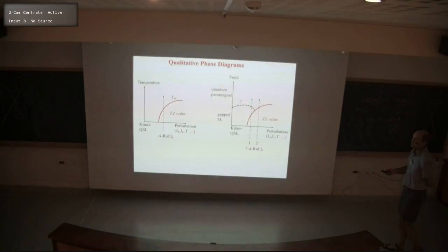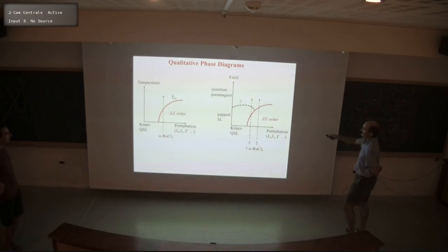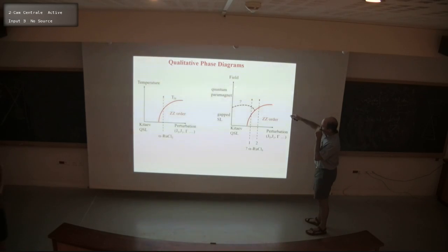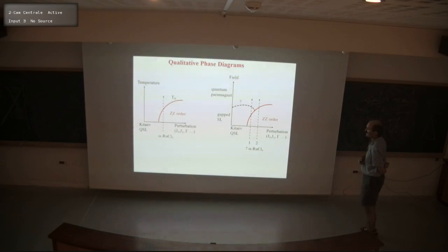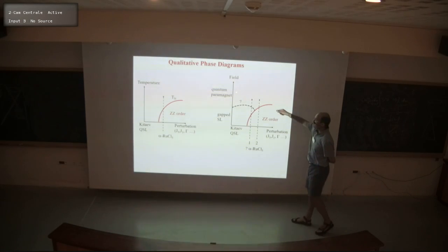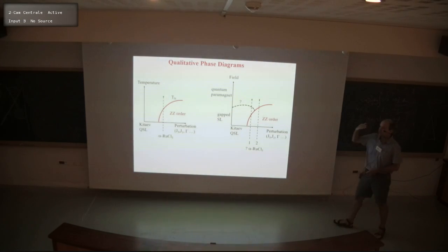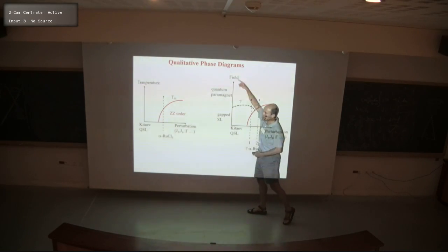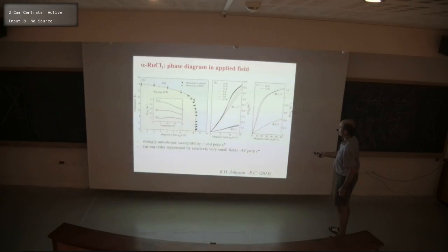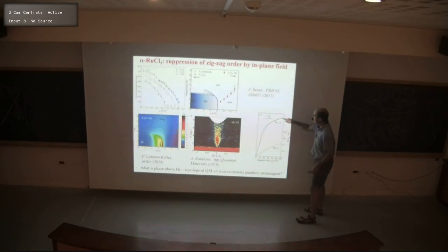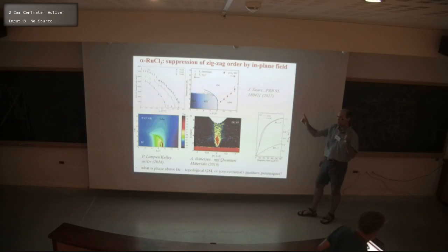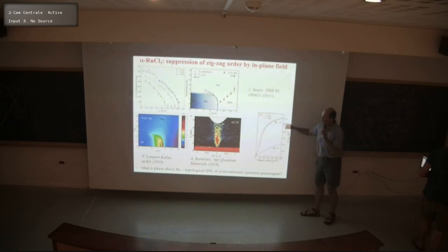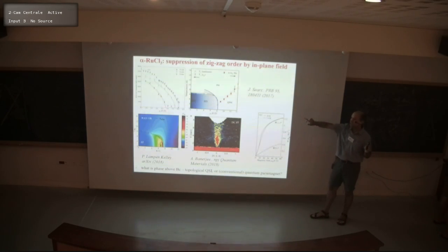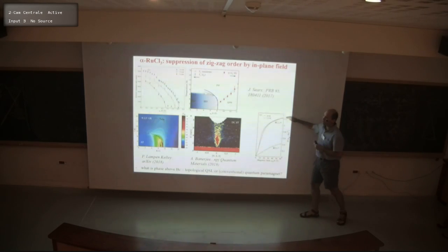What do you call a quantum paramagnet, and how would you distinguish it? So this will be a phase that's continuously connected to the fully polarized phase without a phase transition. So for example, imagine that you start at infinite field where the moments are polarized by the field. And now, if the spin is not conserved, if there is no rotational symmetry around the field direction, there will be zero-point fluctuations building up as you reduce the field.